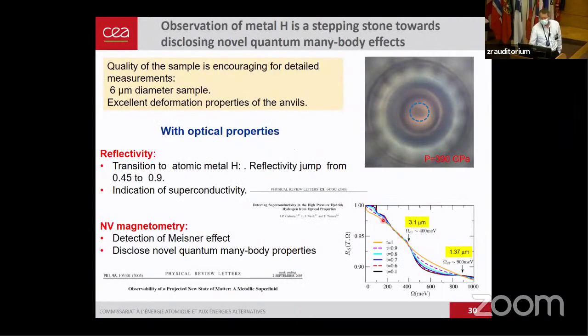Now, what's next? The observation of metallic hydrogen is a stepping stone to disclosing novel quantum many-body effects. The quality of the samples that we have obtained is encouraging for doing more measurements, and we believe that this should be done with optical properties. It's much easier. So the transition to metallic atomic hydrogen should be seen by a reflectivity jump. As I said, molecular hydrogen has a reflectivity of 0.4, and the atomic metal should be very bright, like aluminum, around 0.9. And then reflectivity can also give you an idea of the superconductivity.